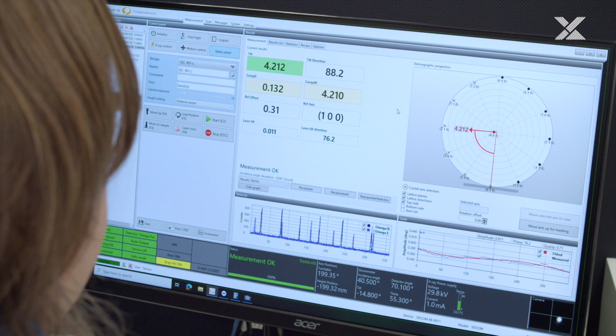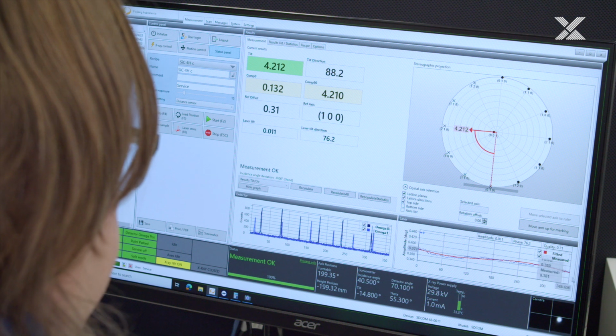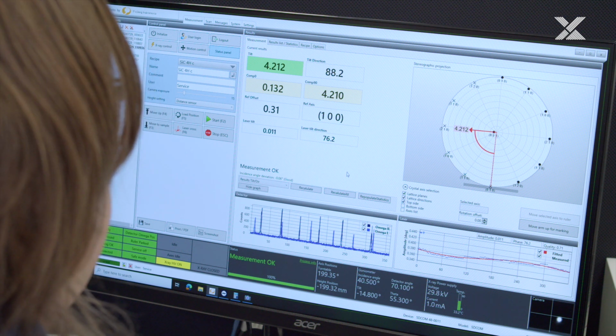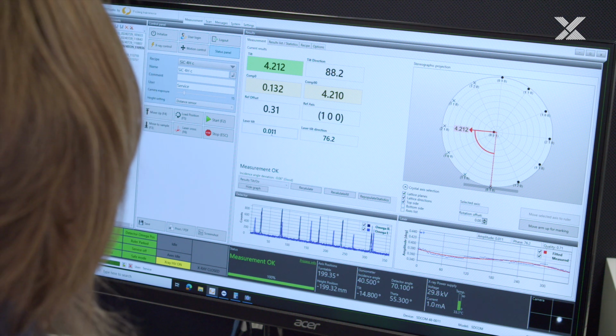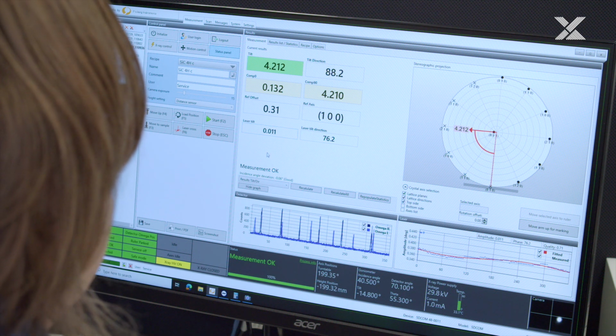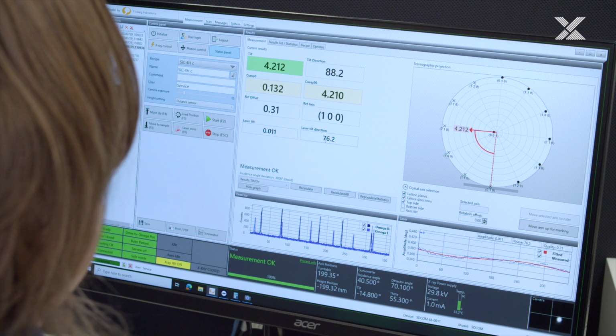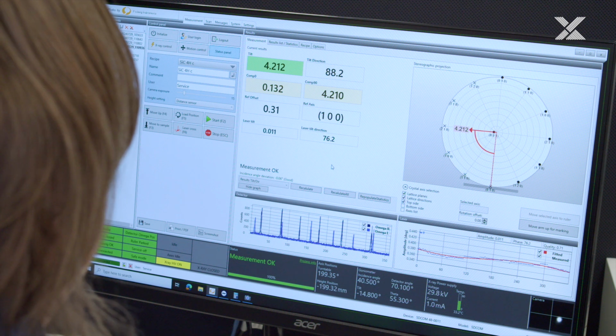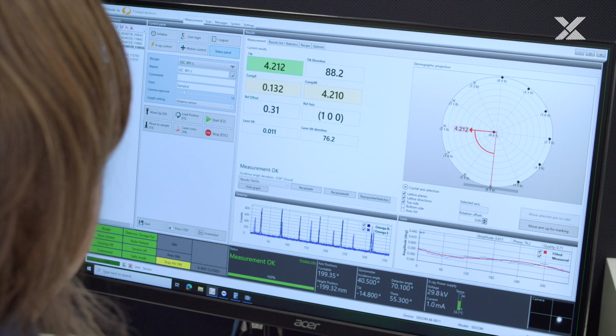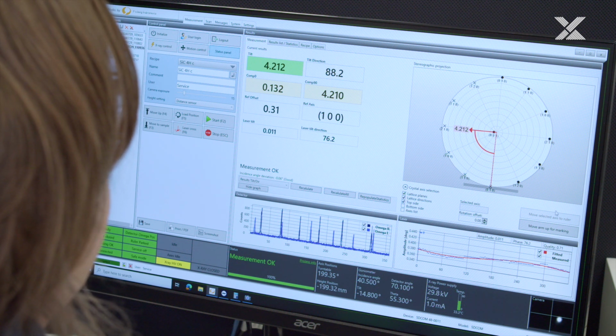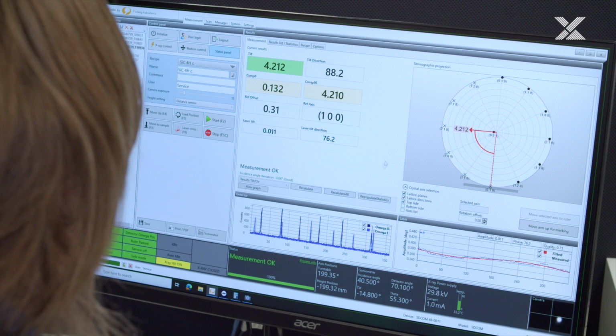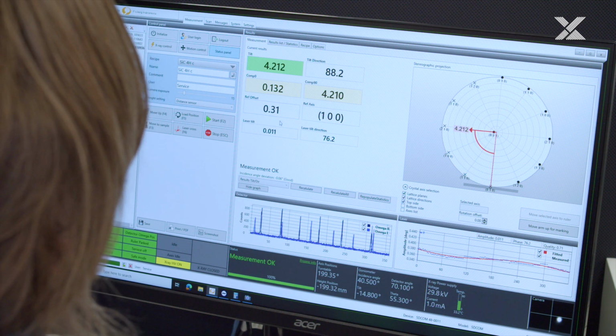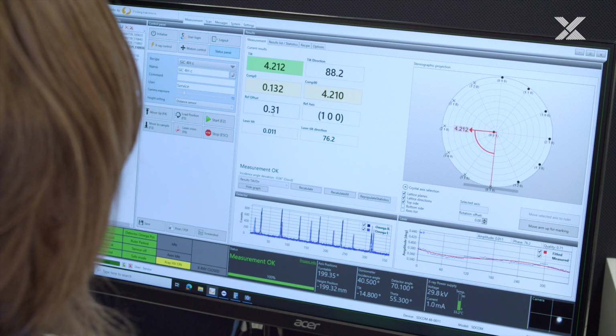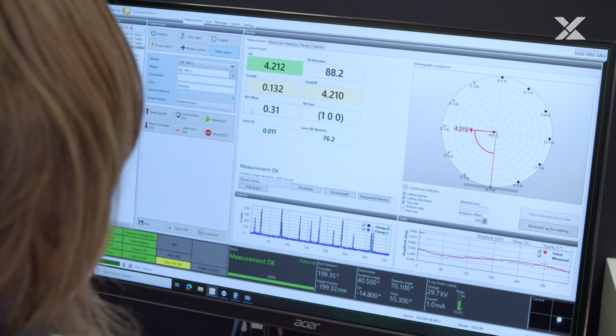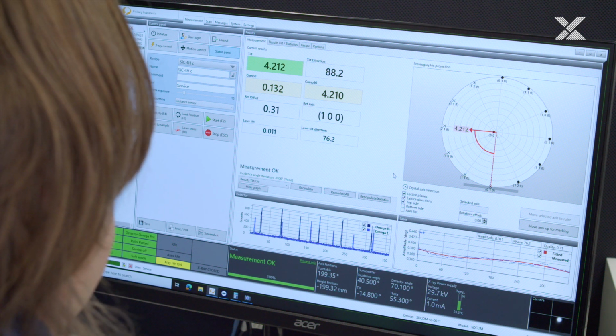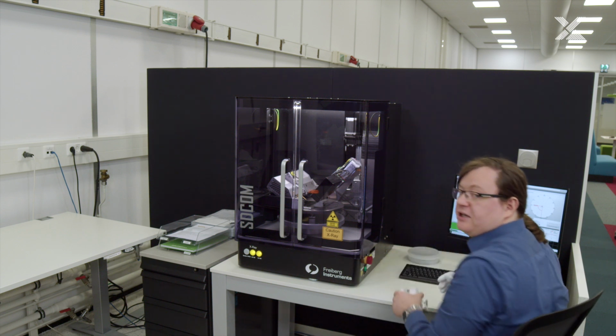And there we go. We've got our laser tilt correction, a minor one, which amounts to about 1/100th of a degree in the direction 76 degrees away from the reference flat. The tilt of our sample is 4.2 degrees, 90 degrees away from the reference bar, and the reference offset, so the angle between the 010 axis and the bar is 0.3 degrees, as it should be. That was the silicon carbide wafer.